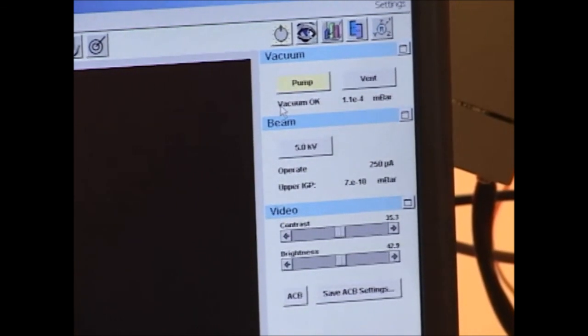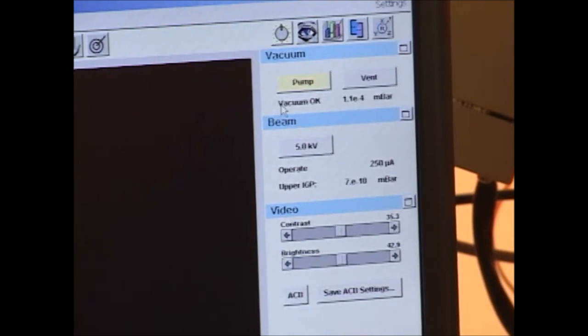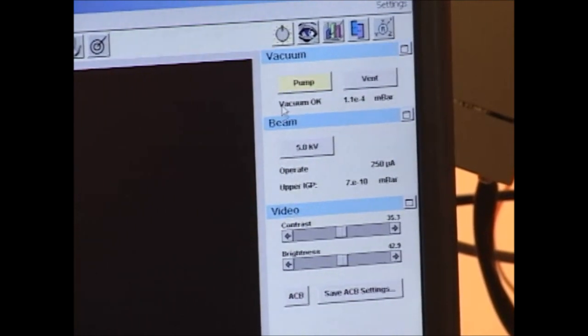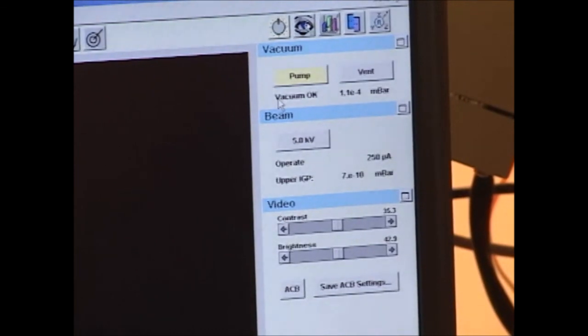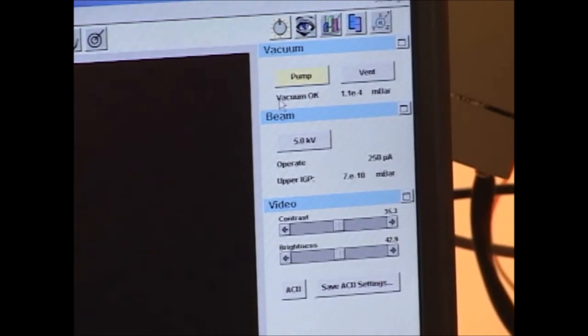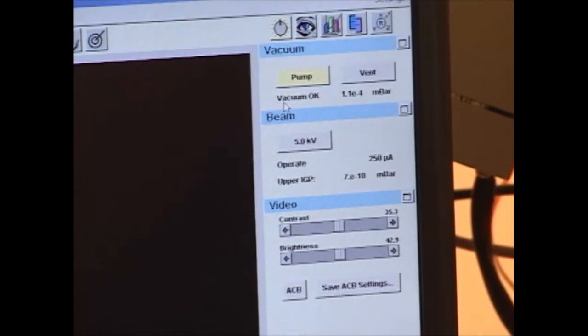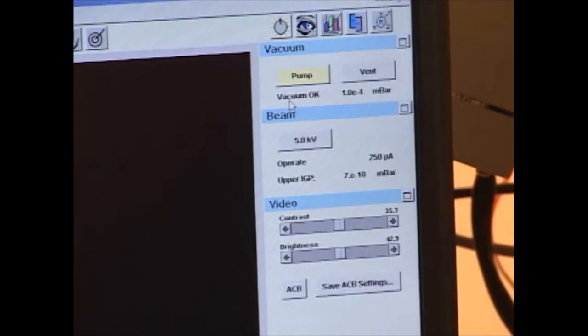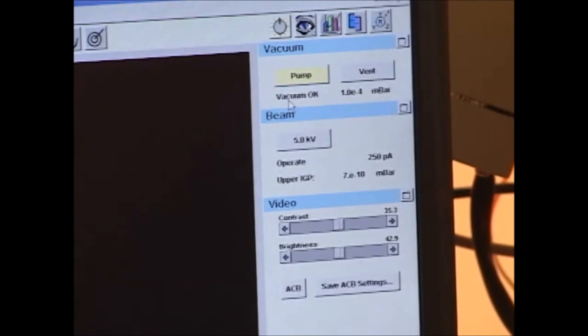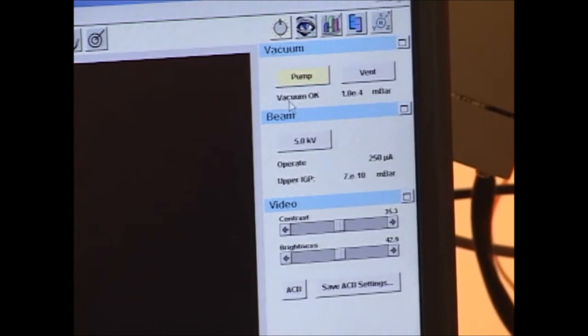The actual reading of pressure in the chamber is not as important as the status message that says vacuum OK. As long as it says vacuum OK, you know the pressure is low enough that you can open the column valve. The upper column where the electron gun is located is at ultra high vacuum. It's usually at about 10 to the minus 10 millibar. If you try to open the column valve before the chamber has reached a low enough pressure, it can crash the vacuum in the column itself. And there's an interlock to prevent that from happening. But that's the indication that we're waiting for, that the chamber pressure is low enough that you can actually open the column valve without affecting the vacuum in the upper column.